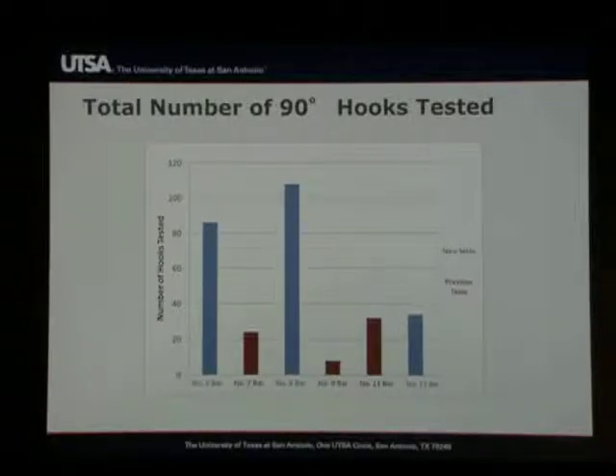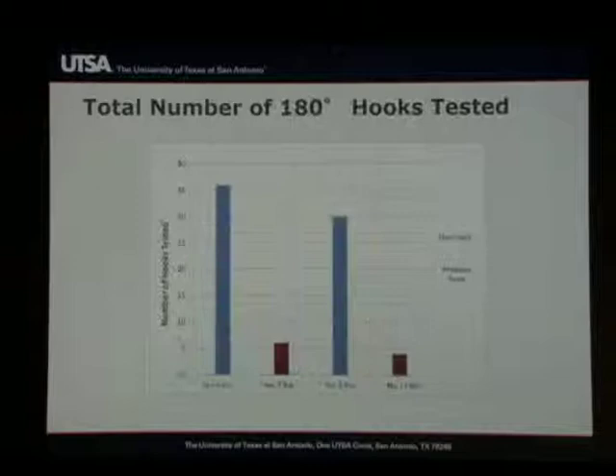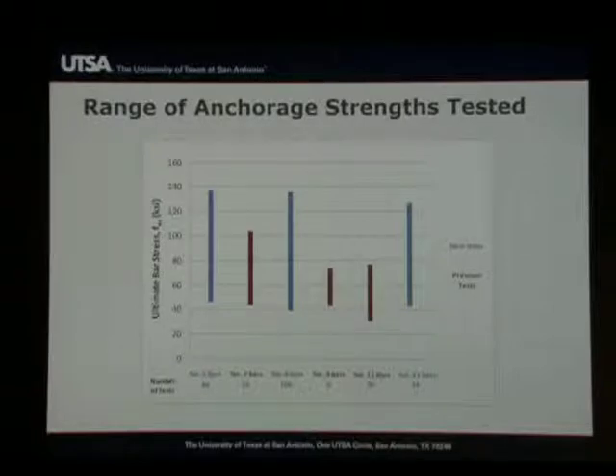And this is for 90-degree hooks. When we look at the problem in the context of 180-degree hooks, the effect is even more overwhelming. We had very few, maybe a total of 10 tests. Now there's a significantly larger number of tests that we have available. But it's not only a matter of having more tests that is important, it is where those tests are targeted. And so we see the breakdown here in terms of bars.